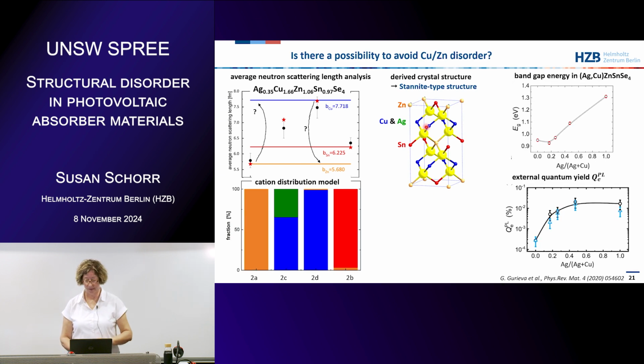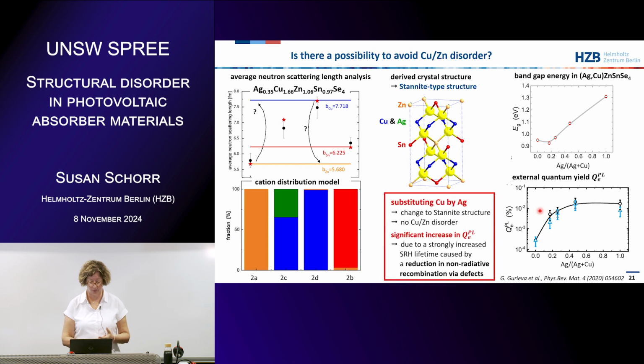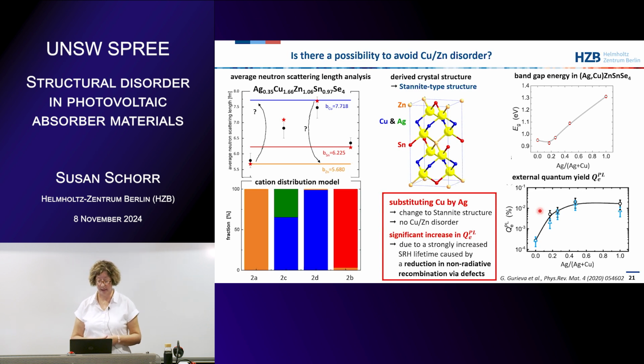And what we found is that, so it's this sample here, I show you, the one here, that we have a massive increase in the PL quantum yield if we introduce silver in the material. And we interpreted this in the way that because we have no copper zinc disorder anymore now, we have this increase here. Possibly this is the reason for it. So if you substitute copper by silver, you will change the crystal structure to the stannite type structure, and there is no copper zinc disorder anymore. And we have a significant increase in the PL quantum yield.